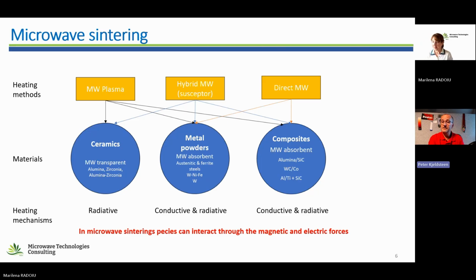But the funny thing was that when I took out the parts afterwards, they were sintered. They were even stainless steel, in air. You cannot sinter that. People are crazy if they try to do that. Normally we sinter in very pure, clean hydrogen, but I couldn't put hydrogen into the furnace when I made these trials. But it worked. And when I could make such a simple test and make it work, I could see potential: if people who knew a little more about it had this in their hands, for sure it could work. Sure.